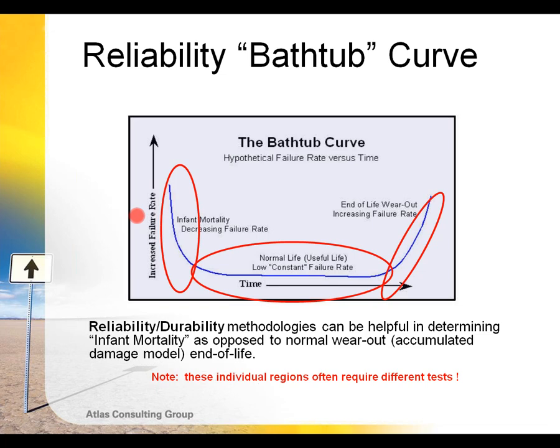And these typical types of tests require a different testing methodology because very often these tend to be defects that are going to be revealed fairly quickly. So after maybe even 10 thermal cycle tests, if there are some solder bond issues, those will typically be revealed very, very quickly in these accelerated life tests.